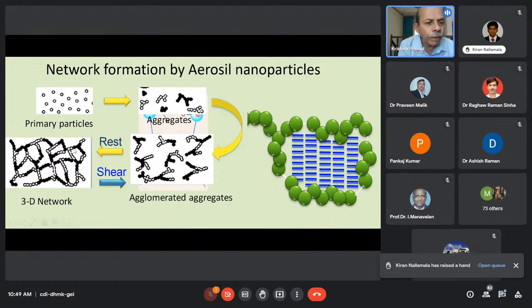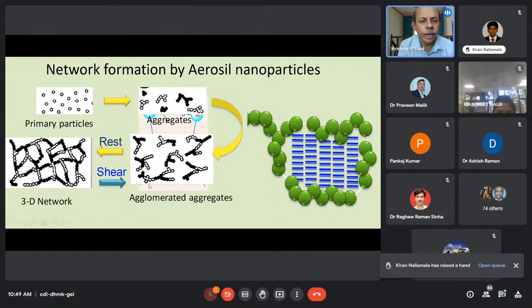So it is the void that I was talking about. It's created by these 3D networks. And now if you apply a shear, the 3D network will go back to an agglomerated aggregate, or if you allow it to rest, it will come back to the 3D network. For example, I have put here an aromatic liquid crystal confined in such a void made up of Aerosil particles. So if I use such particles and put them in a liquid crystal, there is a gel that is formed, a thixotropic gel.